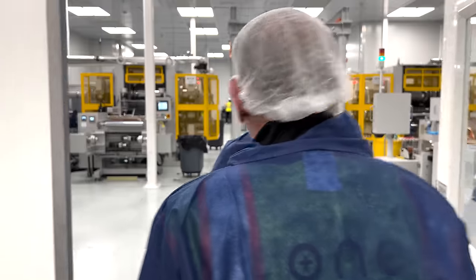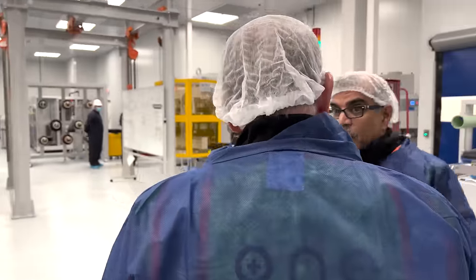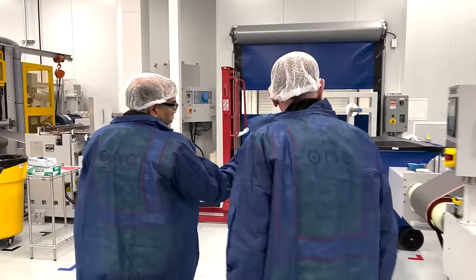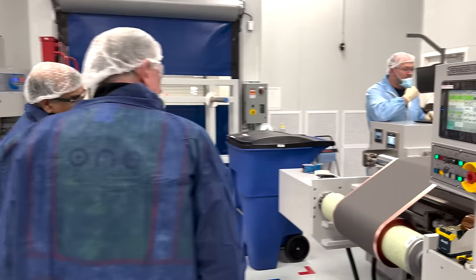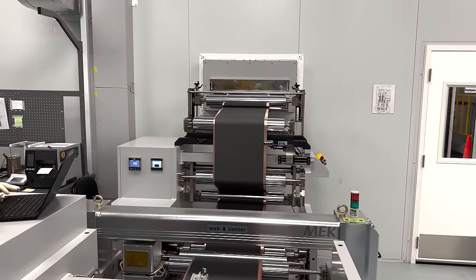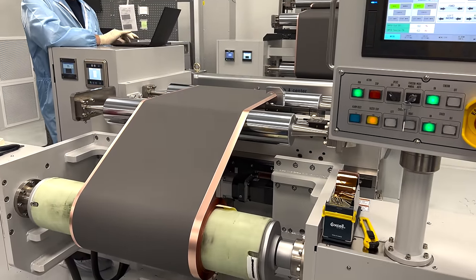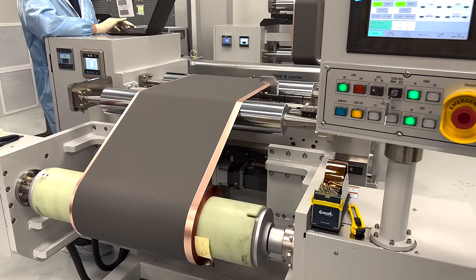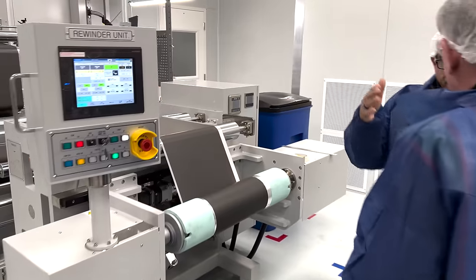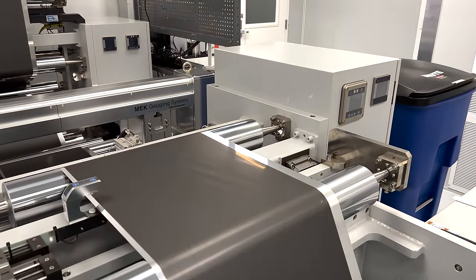Are you going to be making cylindrical cells? No, these are actually metal can for automotive — they call it prismatic, prismatic metal can. This anode material is now coming out dry. That gray represents the graphite. And on the other side, we can show you the cathode material — this represents the LFP. So the LFP is on aluminum foil and the graphite is on copper foil. This is now coated on both sides.